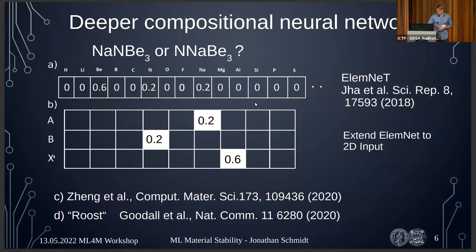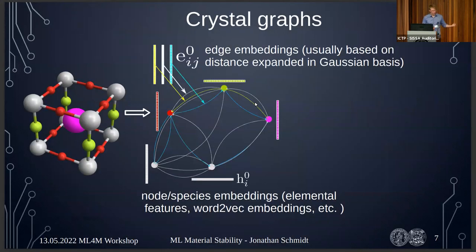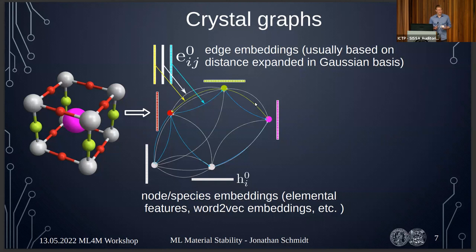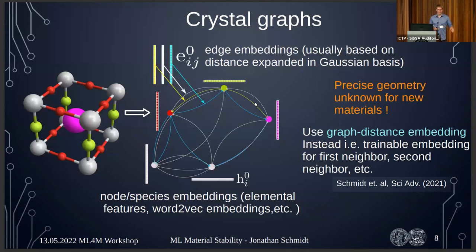You could extend representations to an extra dimension — one vector per site — but then we're limited to one prototype again and can't profit from big data and pre-trained models. We need structure sensitivity, and everyone has heard about crystal graphs: we map atoms of the crystal structure to graph nodes. However, we want to directly predict the relaxed energy or distance to the convex hull of the relaxed structure, but we don't have the right atomic positions.